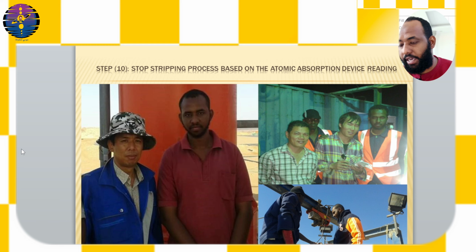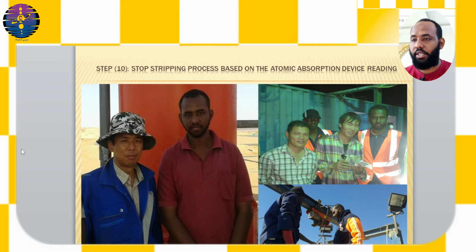Step number 10, stop stripping process based on the atomic absorption device reading. After 10 or 11 hours, the extraction process is typically completed. Samples from the cell's incoming and outgoing solutions are taken to monitor the gold concentration. The process is stopped based on these readings.